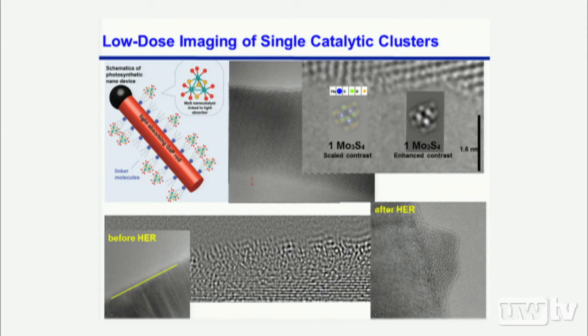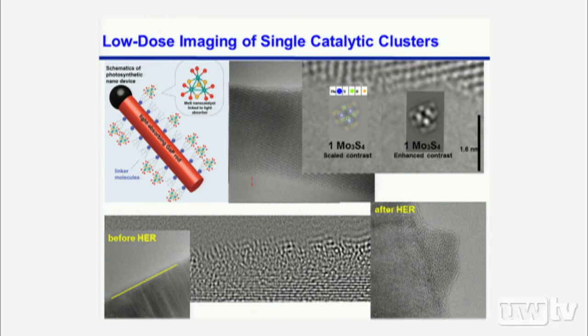Indeed, through more of these experiments, we've discovered that the active water reduction catalyst is the amorphous network of molybdenum sulfide. It's not that the molybdenum sulfide cubane molecules you put in are stable. They typically decompose after the photocatalytic water reduction. In the end, that amorphous network is still very active for water reduction. So that's on the photocathode and the water reduction end.